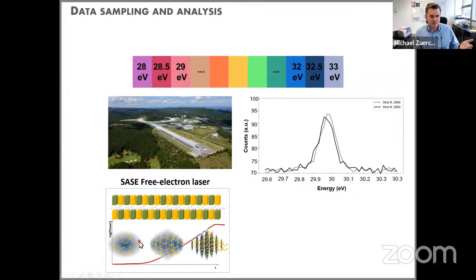It's also called the self-seeding effect in a way. You generate very little X-rays at the beginning, and out of this initial noise, from this initial emission, you get self-seeding, which then gives rise to a very strong amplification of the X-rays passing through the undulator. And this gives rise to millijoule-class or multi-millijoule-class X-rays. The one thing now relevant for our work is that this self-amplified spontaneous emission, SASE effect, which is of course also known from optical lasers, starts from noise.